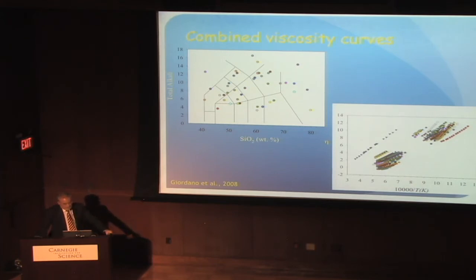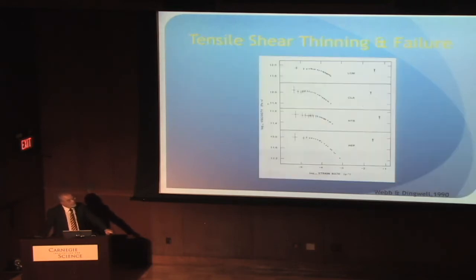And on the lower right, you see what is almost 25 years of experimental work to produce a general model of viscosity versus temperature for these liquids. If you look at the vertical scale, it's log base 10. So you see there's a huge range of viscosity as a function of temperature and as a function of chemistry at any given temperature. Those are Newtonian viscosities. It means no matter how quickly or slowly you deform, you always have the same coefficient, which tells you how much stress you need to push it. But even that breaks down if you go to extreme conditions.